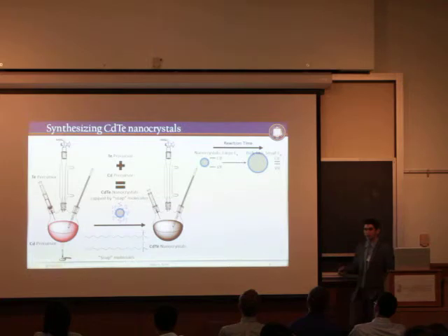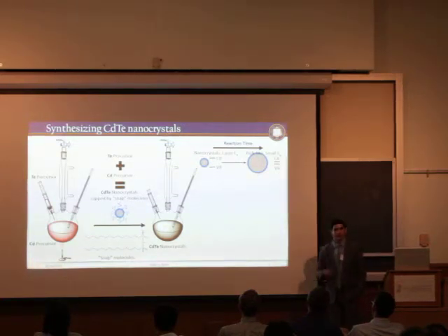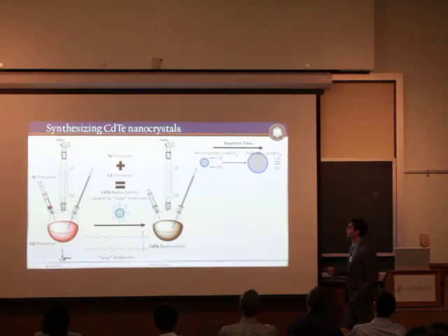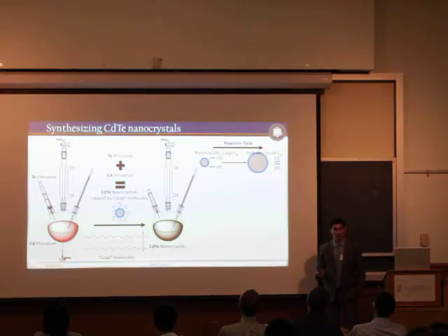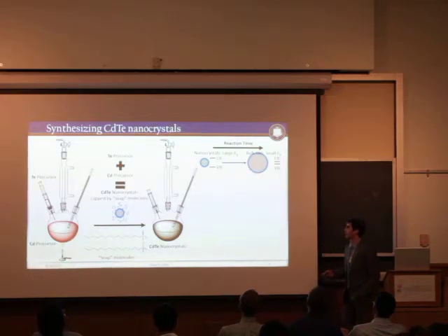Over time, our nanocrystals grow. And because they're on the nanoscale, they obey a rule called quantum confinement. Essentially, at smaller scales, our band gap is larger. So you need higher energy, or lower wavelength, light to excite our electrons from our valence to our conduction band. Over time, these crystals grow to larger and larger nanocrystals, almost bulk-like, and they have a smaller band gap, which essentially means lower energy, or higher wavelength, light.